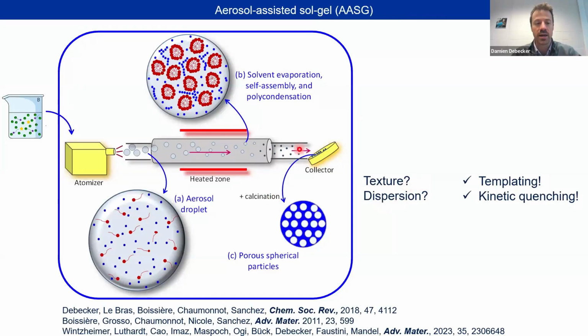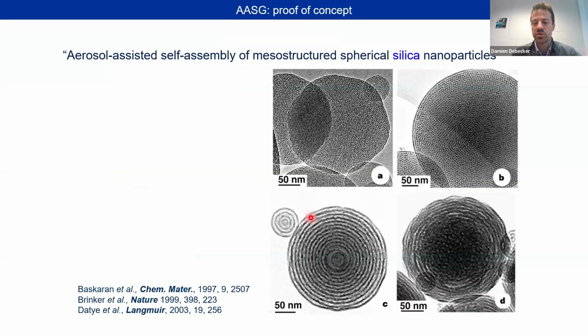You can control the texture by choosing carefully your surfactant. And what is really nice is that you can control the dispersion because you have a kind of kinetic quenching. Even if the reactants react at a different pace, they don't really have the time to find each other and to form inclusions. You will quench, you will freeze the system in a homogeneous dispersion here in a mixed oxide. So the first proof of principle of those aerosol-assisted self-assembly of structured materials was shown on silica 25 years ago, as you can see there.